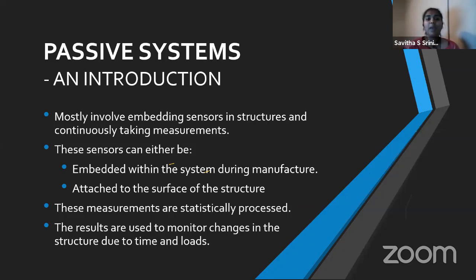So when we embed these sensors inside the systems, we tend to have nearly a 50% loss, which means that these sensors are very delicate pieces of machinery and they're really small, and they kind of tend to get dislodged during the manufacture process. So anyone who's ever been to a construction site knows that when they're pouring concrete or attaching rebar, it's not like they're going to be very careful with it. They'll just pour it. So these sensors need to be handled with care. So they tend to have a high loss rate. They can also get destroyed during placing or after placing as well.